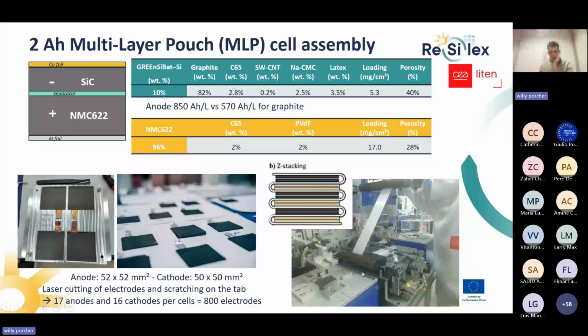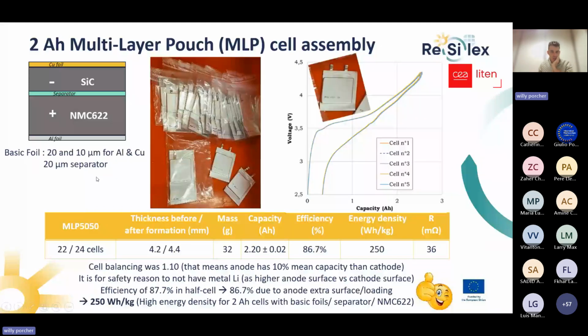For cell assembly, we use a stacking machine. You have here the negative electrode, positive electrode, and we have a Z folding process, the Z folding of the separator around the electrodes to avoid short circuits. And at the end, having some cells. So we assembled 24 cells, 22 without, I want to say, current leakage, 22 with a high quality. Thickness was 4.2 millimeter after assembly and 4.4 after the first cycles. 32 grams per cell, and a capacity of 2.2 ampere hour with low deviation.